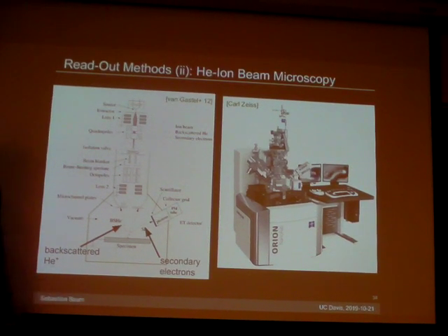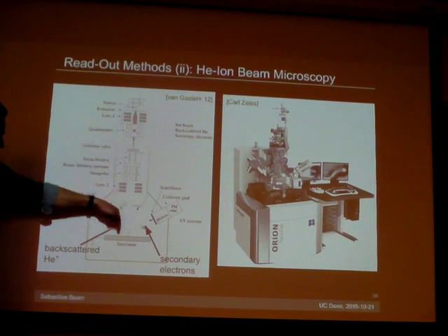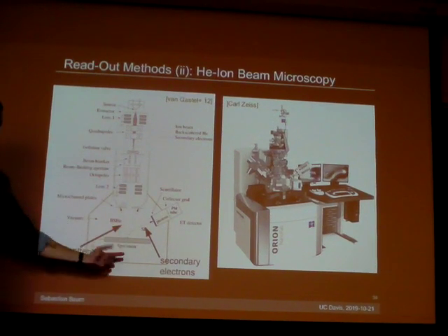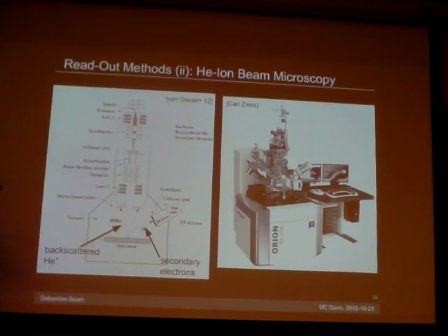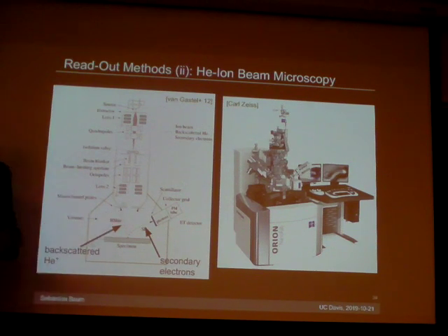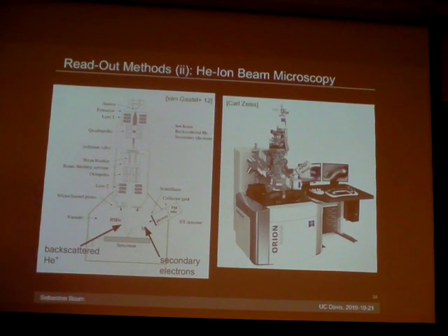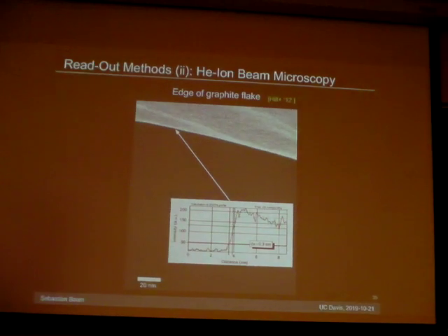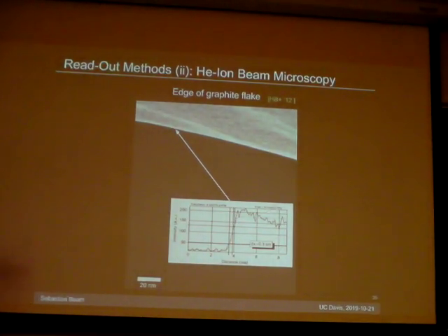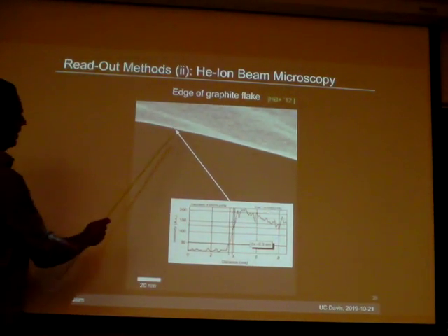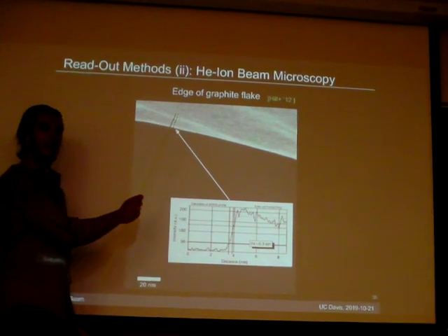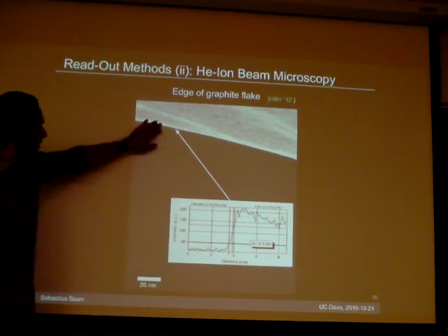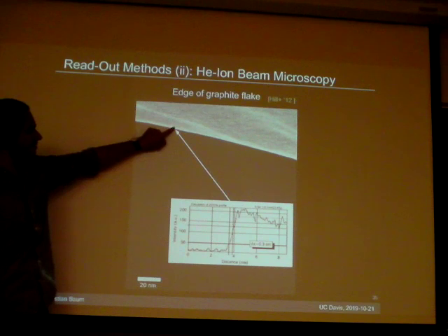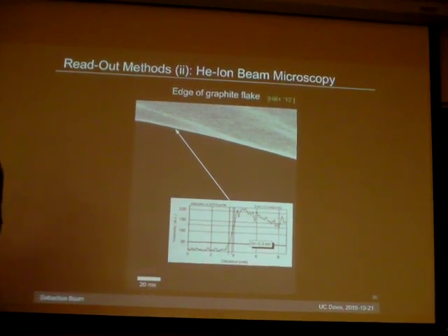And what you do essentially is you shoot a low energy ion beam at your target, low energy helium ions, and you measure backscattered helium ions or electrons being emitted from the surface. And what that allows you to do is to achieve nanometer scale resolution, right? So this is a graphite flake they built, and they've only taken this picture to demonstrate how well this helium ion beam microscopy works. They've demonstrated 0.3 nanometer resolution of this edge of the flake.